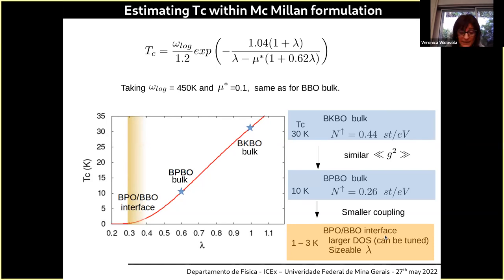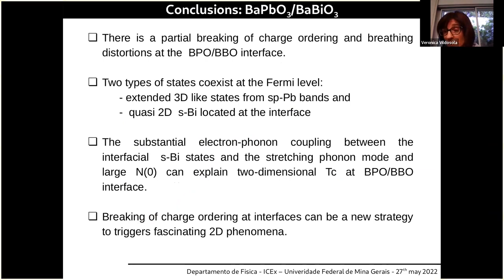So what we are claiming here is that we can explain the two-dimensional superconductivity in this bilayer of BBO with BPO with the fact that there is a partial breaking of charge ordering and breathing distortions. There are two types of states: quasi-two-dimensional, which are the ones that couple to the phonons at the interface, and three-dimensional, which do not contribute to superconductivity. And there is substantial electron-phonon coupling between this interfacial stretching phonon mode that can explain the two-dimensional critical temperature in this interface, in this bilayer. And what we claim is that the breaking of charge ordering at the interfaces can be a new strategy to trigger fascinating 2D phenomena. I'm finishing.